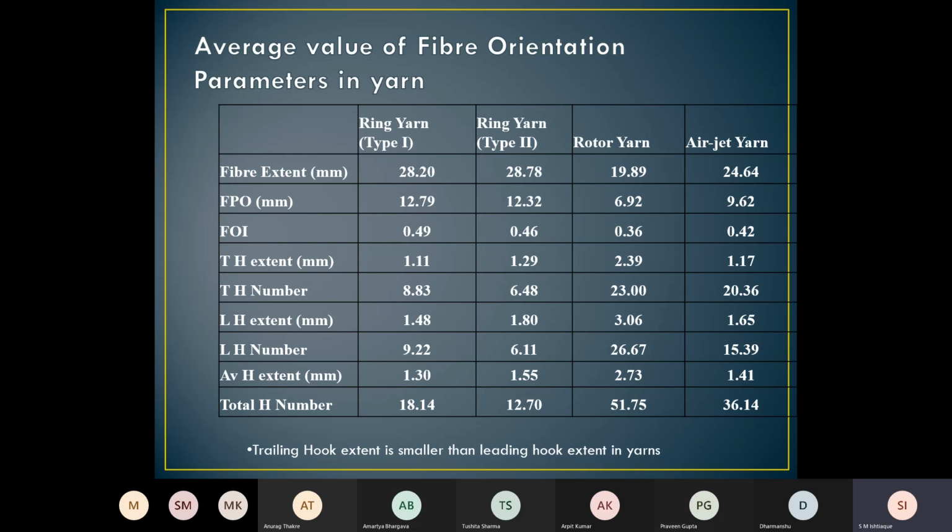At the same time, fiber straightening is also taking place. So fiber extent will also be more with higher spindle speed, which means the spinning coefficient is more. Packing density, you said, is more, but practically you'll find that higher spindle speed gives you lower strength.